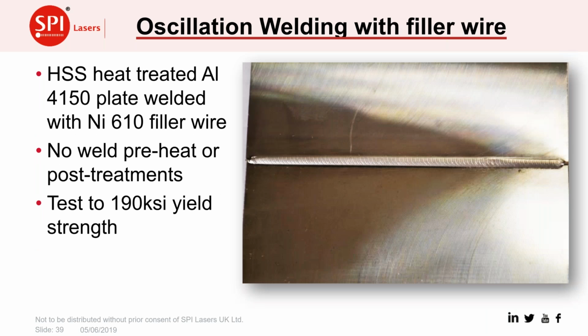Sometimes we can use a filler wire, and this joint here was done. We made a very strong weld. We did use a filler wire in this application, which was placed on the surface as we welded along. This is the weld as it came out with no preheating and no post treatments, so it's produced a very good quality weld where the filler wire has been incorporated into the joint between the two parts.